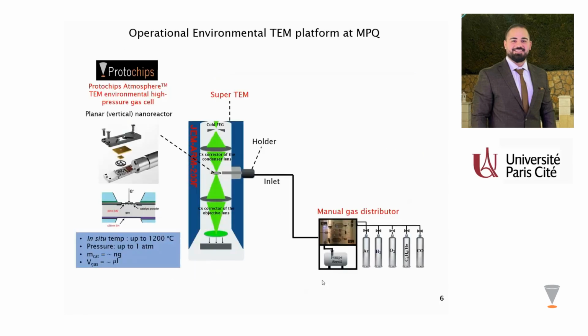So of course, to achieve all this study, we need a good setup. That's why all our environmental transmission electron microscopy studies have been done using the Super TEM JEOL ARM 200F, having a double aberration corrector of the objective and the condenser lens. To monitor the catalysts during gas phase experiments, we use a Protochips Atmosphere gas holder dedicated to the study of catalysts in gas environment and having a high pressure gas cell. This cell allows us to heat the catalysts up to 1200 degrees Celsius and the inlet of the holder can be coupled to a manual gas distributor, which allows us to introduce the gas to the cell up to atmospheric pressure and then to obtain the real catalytic condition.